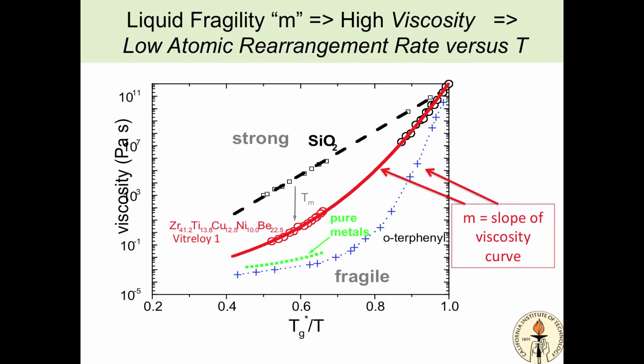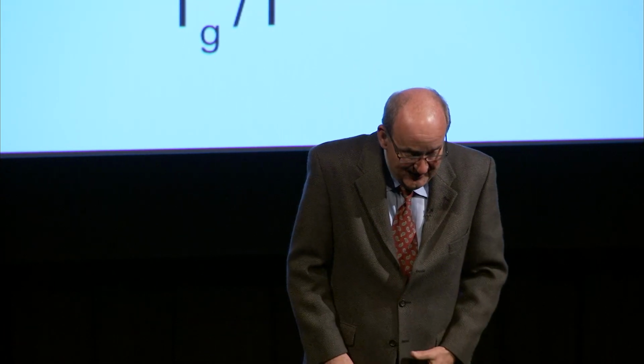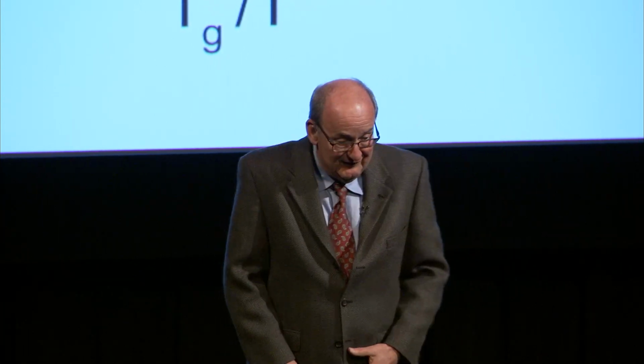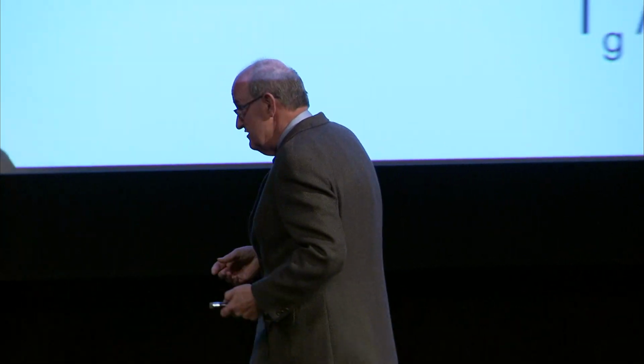Well, let me show you. Once you learn more, you do your science and figure out how this viscosity story works. And I don't want to spend too much time, but when you heat a liquid up, all I want to show you here in the viscosity is that at the glass transition, the viscosity is 1 trillion Pascal seconds, in some units. And if you have a high temperature liquid, it's 1/100th of a Pascal second. So when a liquid freezes, the viscosity, or its resistance to shear, changes by 1 trillion times as you cool it down. So this freezing is incredibly rapid. It's like the standing room only crowd. As you squeeze people together, the possibility of rearranging yourself gets frozen out very rapidly. It's called jamming. It's called a jamming transition for obvious reasons.